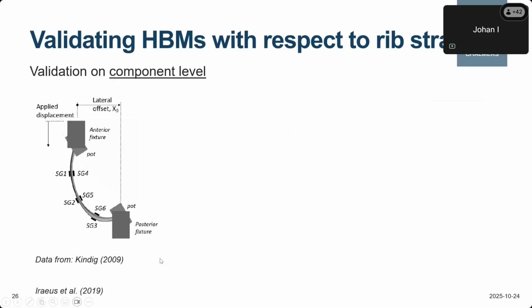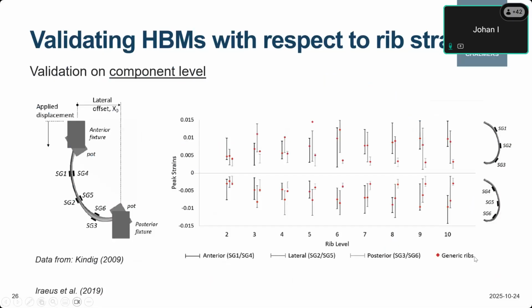So one example here is Kindig. During his PhD, he did isolated ribs in anterior-posterior bending. He had 6 strain gauges, and by simulating this with, in this case, the generic ribs from the SAFER HBM, we could show that the red dot here, the result from the simulation model, falls within the interval of the tests. And to be fair, those intervals are very wide, except for some spots here. But this is at least the first indication, so we are in the middle of the range from the physical test.